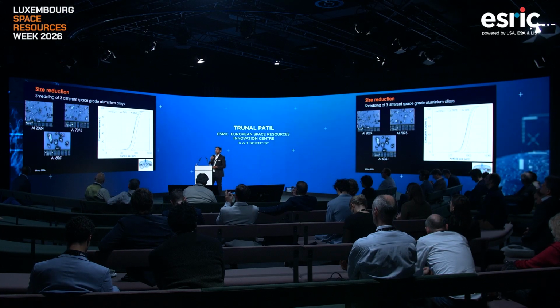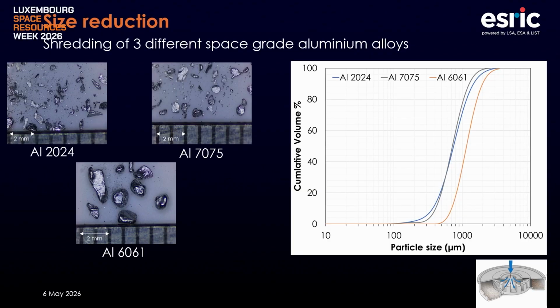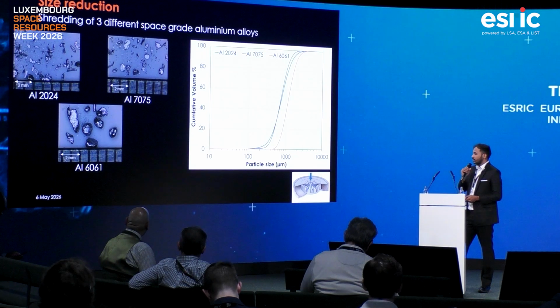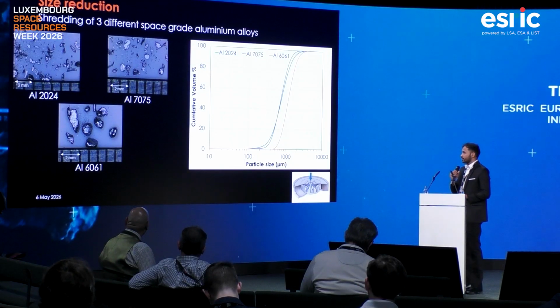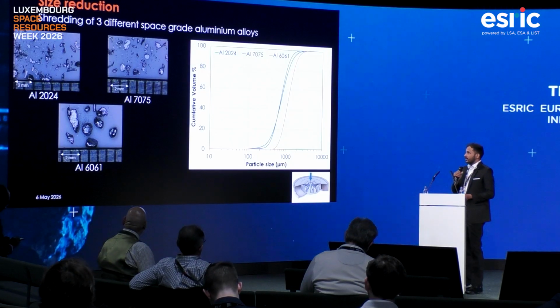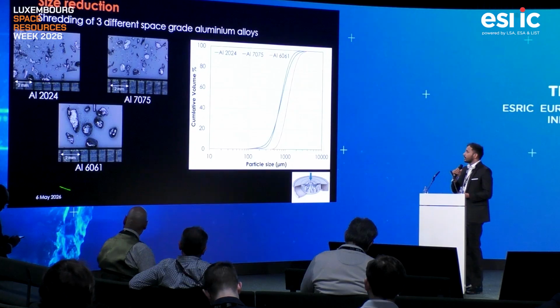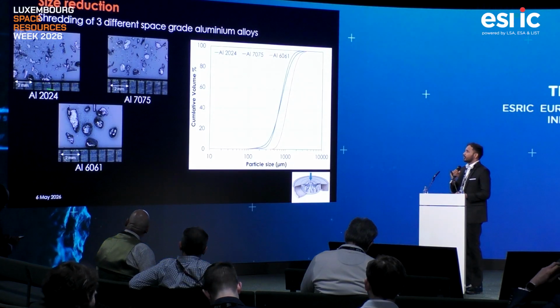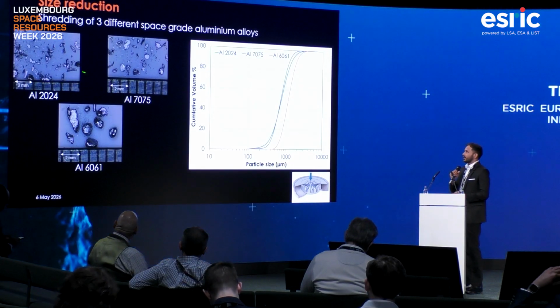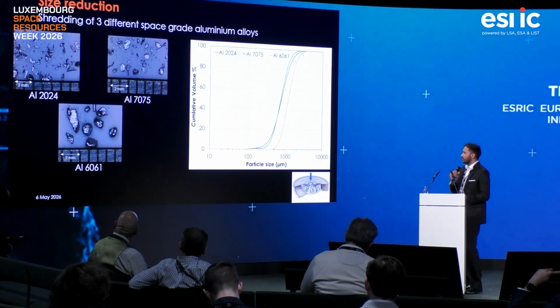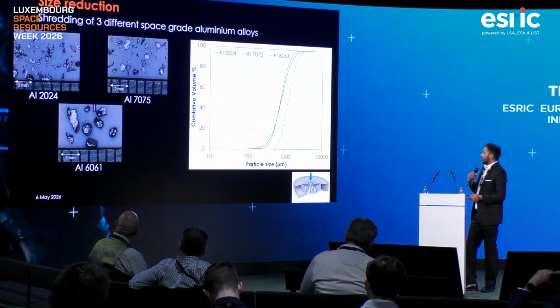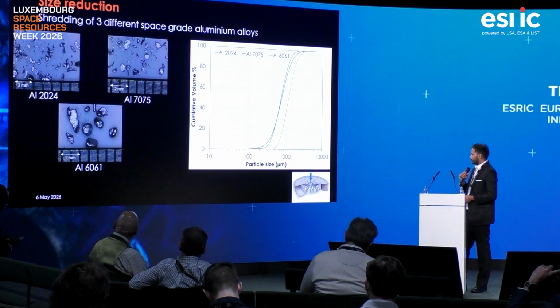So interestingly, even though they are all aluminum alloys, we found very interesting results. Aluminum 2024 and aluminum 7075 processed successfully, but in the case of aluminum 6061, we found jamming issues. As you can see in the pictures, the aluminum 2024 and aluminum 7075 particles are a bit smaller compared to the 6061, and you can see this in the particle size distribution as well.